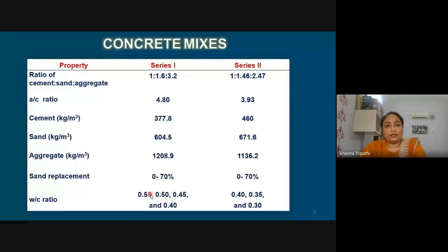Next, coming to the mix, we had studied two kinds of mixes, one with a higher aggregate cement ratio and one with a lower aggregate cement ratio. In the higher aggregate cement ratio, we had studied four kinds of water cement ratios, and in the lower aggregate cement ratio, three kinds of water cement ratios were studied.